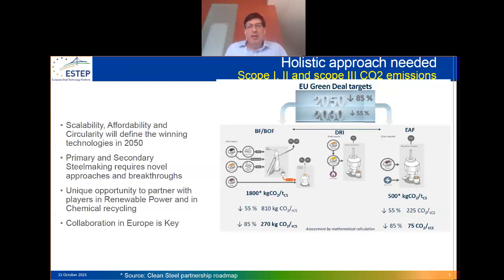If you look into the translation into real figures on the right side, the left one is the primary production, starting with BF-BOF, blast furnace, basic oxygen furnace. Typically today it's around 1,800 kilograms of CO2 emissions per ton of crude steel. And following the objective Andrea pointed out of the Green Deal, we have to go down by 55%, meaning 810 kilograms emissions. And climate neutrality is then something like going down to 85–95%, and 85 means 270 kilograms of CO2 emissions. So these are really huge challenges lying ahead of us.